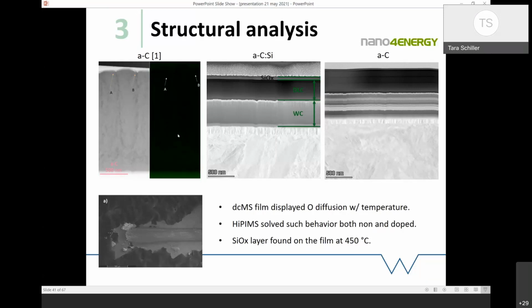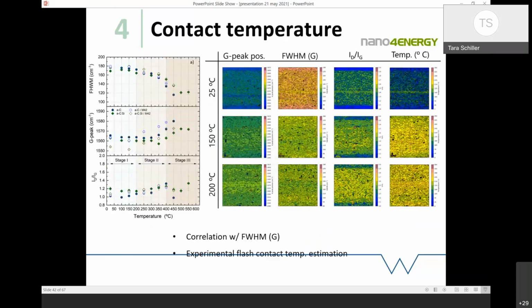One of the things that we do is look at the wear track, but measure it over a range of temperatures. So we're looking at what happens to the film, how it destroys, whether doping it with silicon helps, and basically what changes we're seeing and how much oxygen diffuses through the materials as well. The good thing about this is the PVD technique, the HiPIMS, worked quite well at improving the properties overall of the material, which was quite a nice output of this. These TEM images just came out really well. One of the things I mentioned earlier was looking at